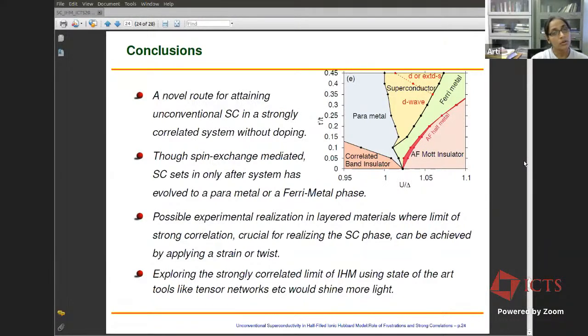And although the superconductivity is induced by spin fluctuations and by the spin exchange interaction term, interestingly, the superconductivity appears sandwiched between the paramagnetic metal and the ferrimagnetic metal on both sides, which makes this phase diagram very different from the phase diagram of any known unconventional superconductor that we are familiar with today.